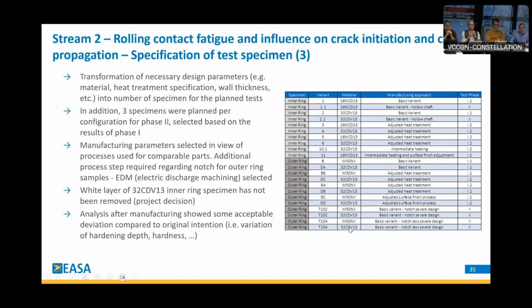A transformation of all of these aspects was necessary with regards to the number of specimens that we needed. So you have seen that we have heat treatment, design parameters, and so on. But of course, we need to select the number of test specimens in a way that we can handle it in the project time and in the project scope. Based on this number of samples, we said that we will spare 3 additional specimens for phase 2 for the complex load, but selected based on the results of phase 1.